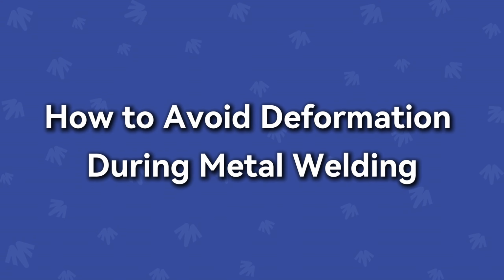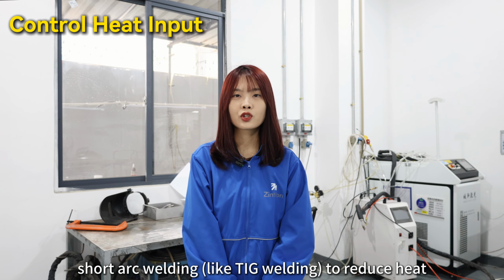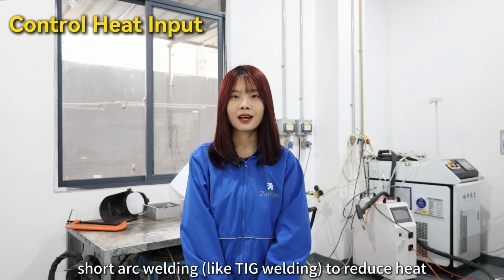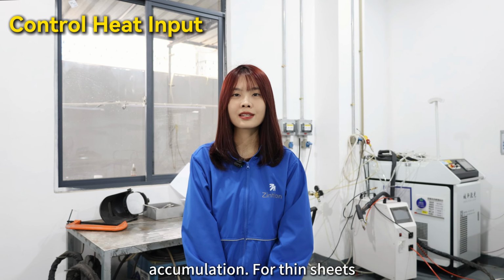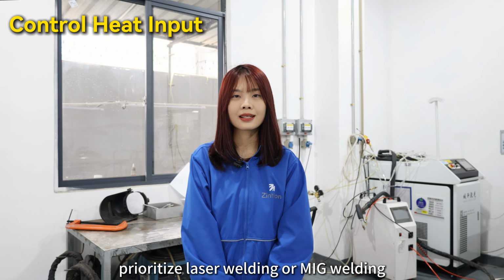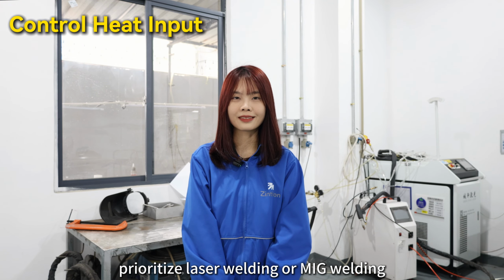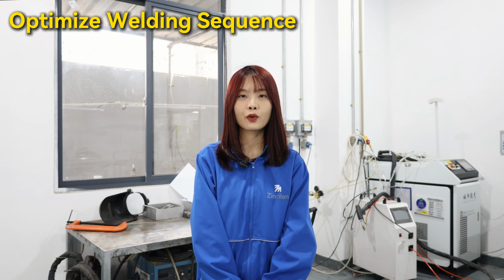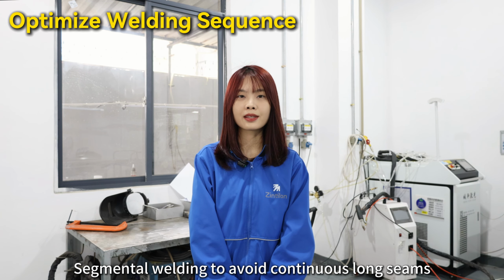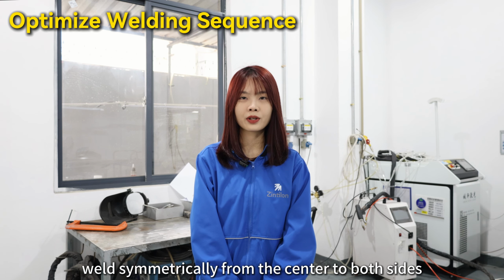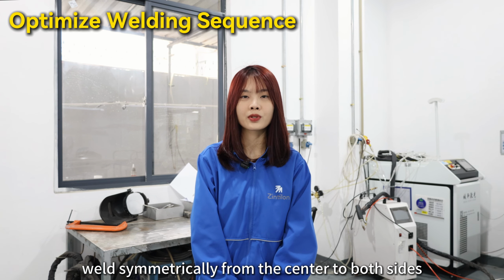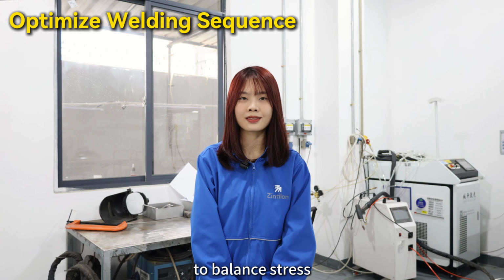How to avoid deformation during metal welding? Control heat input. Use low current, short arc welding like TIG welding to reduce heat accumulation. For thin sheets, prioritize laser welding or MIG welding. Optimize welding sequence. Use segmental welding to avoid continuous long seams. Weld symmetrically from the center to both sides to balance stress.